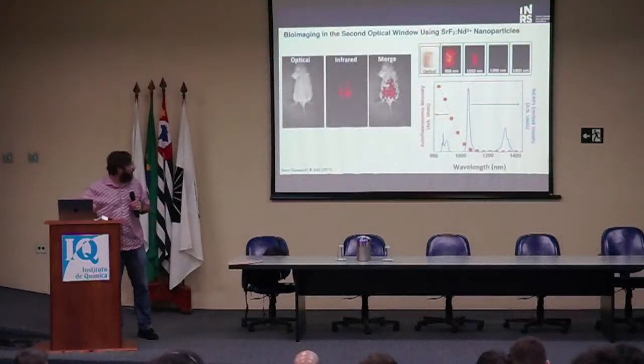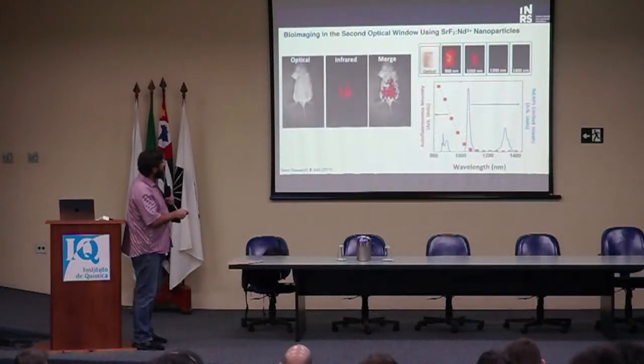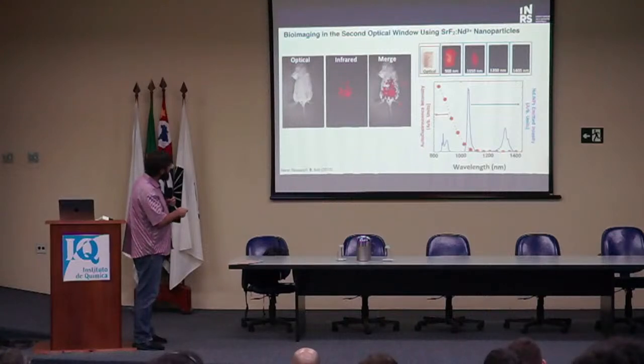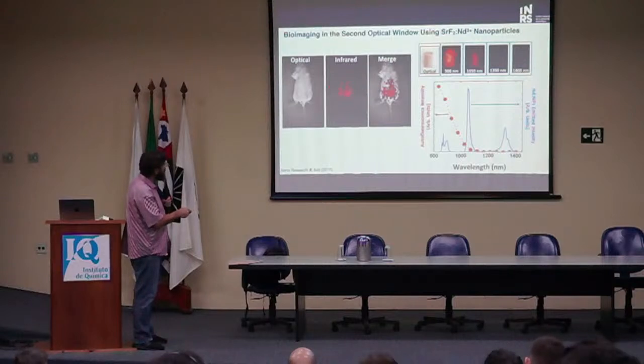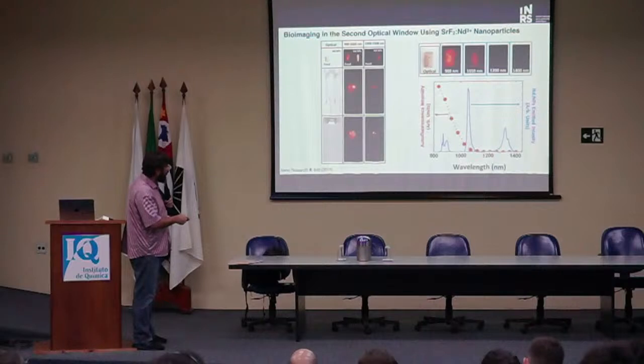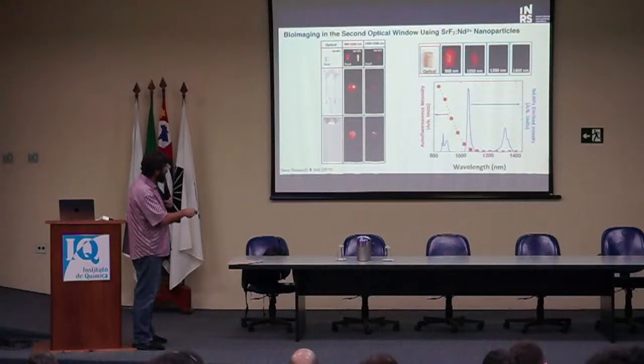But before that, we looked at imaging. We looked at imaging using neodymium, and we wanted to see if we can do whole animal imaging with neodymium-based nanoparticles. And we did, of course. What we didn't know is that we got this really broad absorption in our spectrum. And so when we actually did the imaging of the whole animal, we got this blob here that incorporated the background. And we didn't know why.